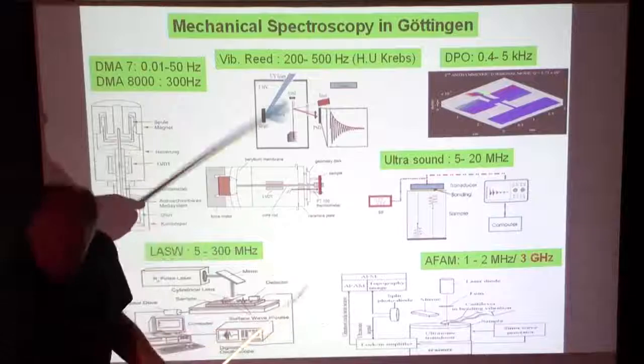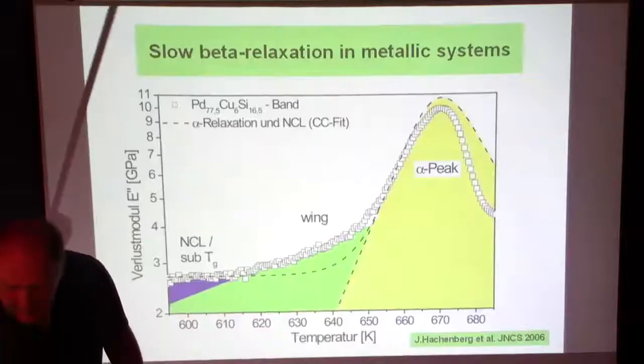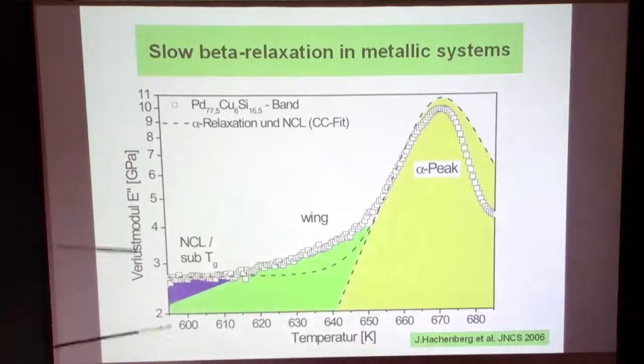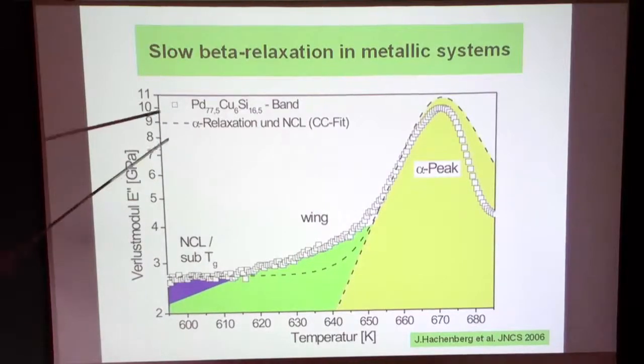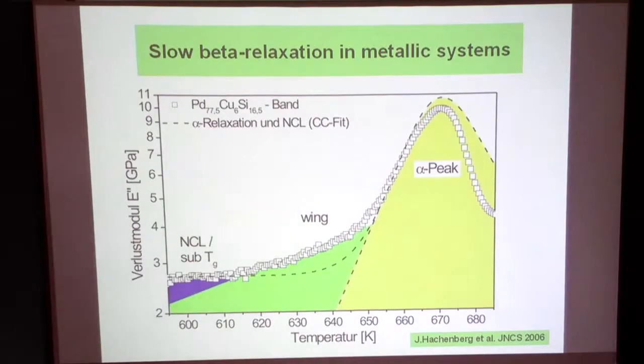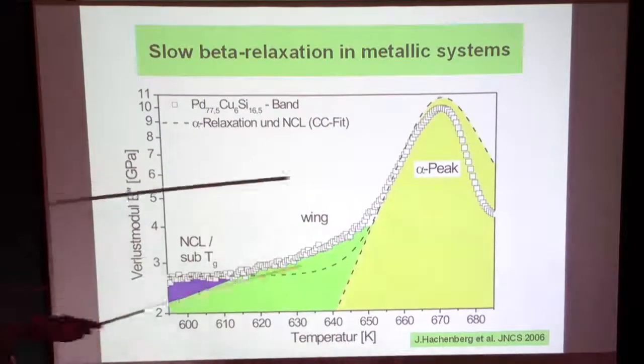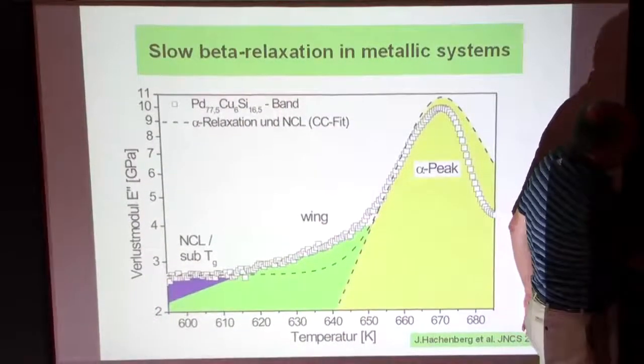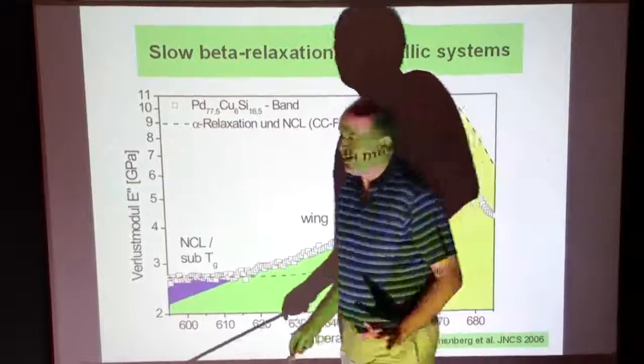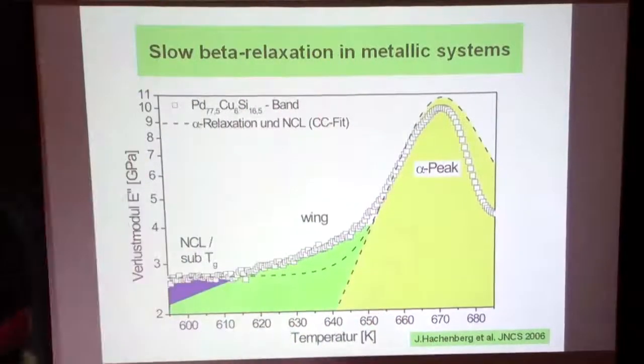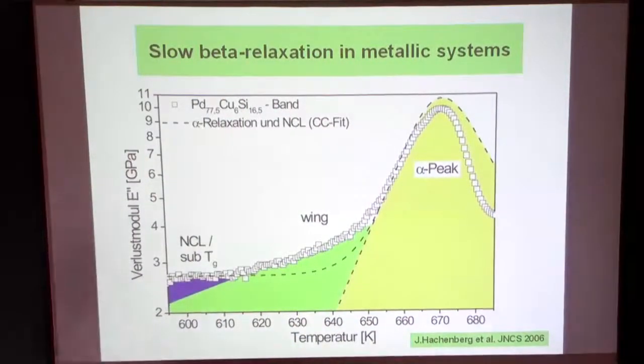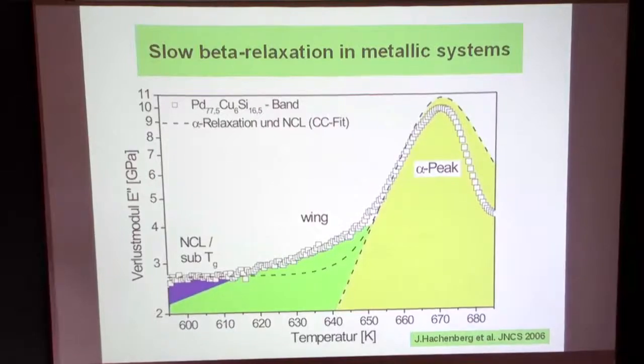This one I come to later on. Here we go. This was quite some time ago. First measurements on this palladium copper silicon system. So we distinguish between those which are more fragile in the sense of the Angell plot here, more like orthoterphenyl, the Vogel-Fulcher law, and ones which have an electron system which is more spherical, s-like orbital, so to speak, and bonding.